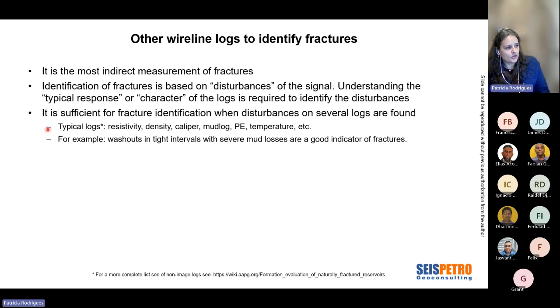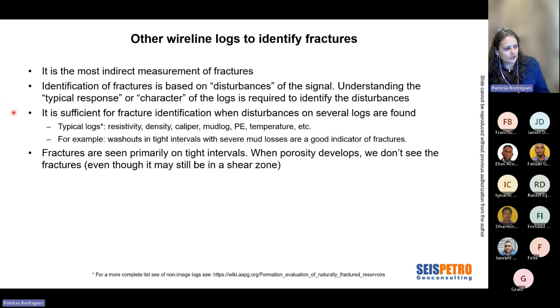Typical logs that are used are resistivity, density, caliper, mud log, PE, temperature, etc. For example, you can find washouts in tight intervals in a carbonate that have severe mud losses, and you can classify that as a good indicator of fractures, because it's tight, so you know the losses are not due to porosity, so they must be due to fractures. The fractures are seen primarily in tight intervals. I'm going to show you an example.